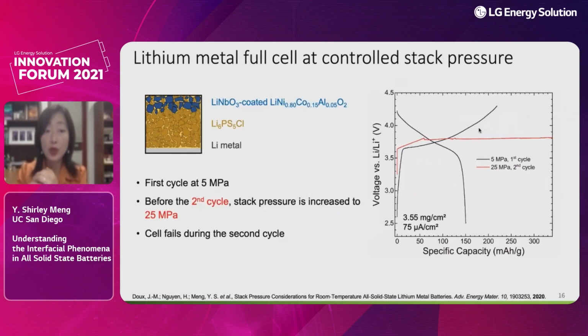So with that, we also want to say we are running into a dilemma. We actually have to put the pressure quite low, but as soon as we increase the critical current density, or put the stack pressure up because we want a very tight contact between the solid electrolyte and the cathode, we run into the trouble of shorting. So it seems like we do need a brand new anode strategy.